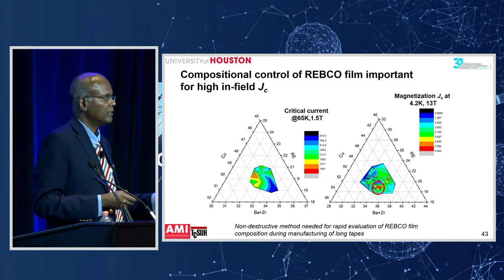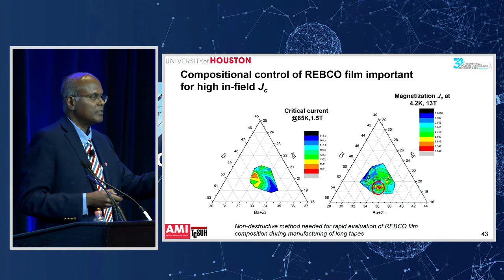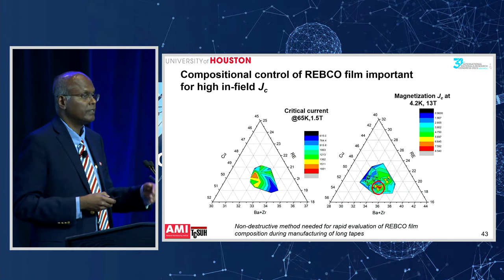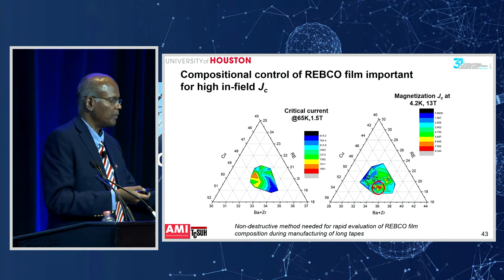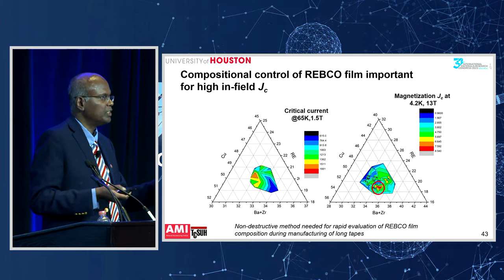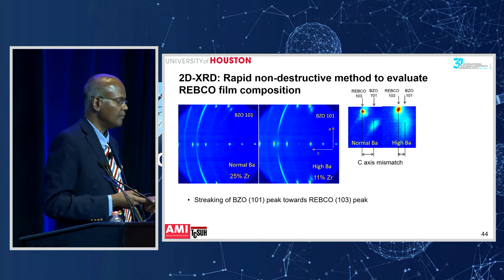And all these measurements are done by ICP, inductively coupled plasma spectroscopy, which, as you know, is a destructive process. So you cannot really control the composition by a destructive process. You need a non-destructive way of measuring the composition in real time as you make the material so that you can control the process. So that's the next challenge. Fortunately, we're able to identify one method that can do that.